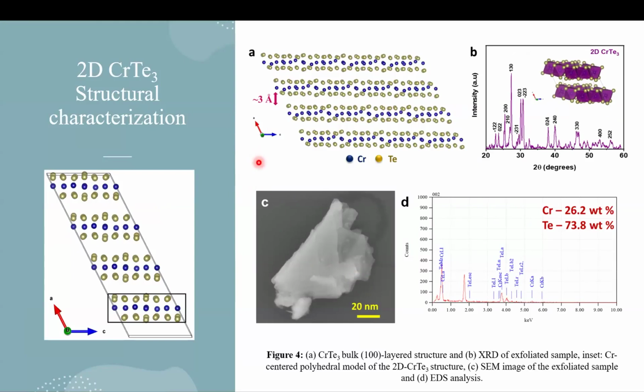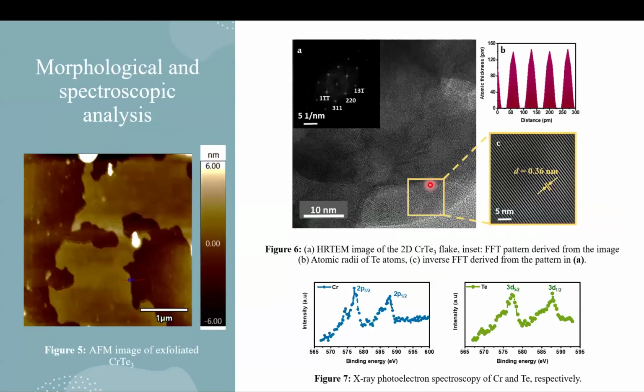And once the liquid is rested for more than 24 hours, we collect the centrifuge supernatant on top of the solution, and we use this material for device fabrication. And then analyzing further the morphological aspect of the material, we were able to see that the lateral dimension of each of these flakes is quite wide, and the thickness is about 4 to 6 nanometers. And we did other spectroscopic studies as well to confirm its chemical composition, even when it is liquid phase exfoliated.